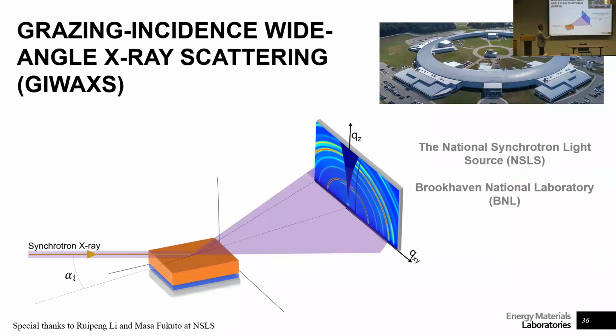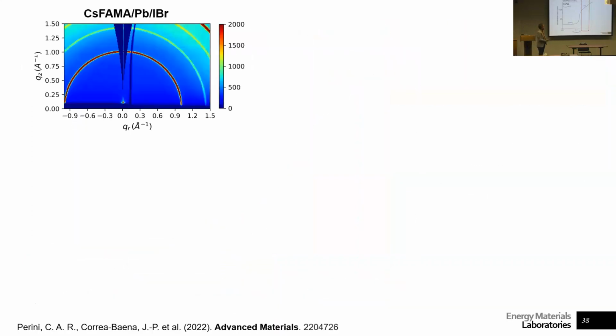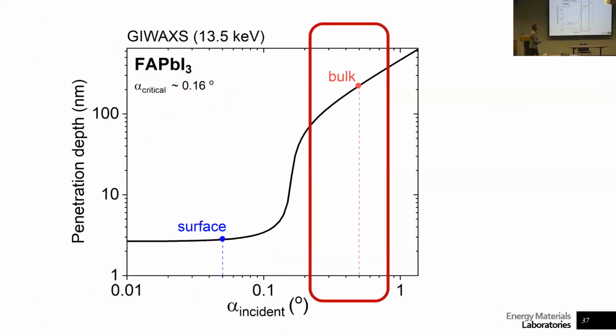And that scattering gives us a signal, and that signal tells us what structures we have in our device. And this is called GIWAXS. And so the lower the angle here, the more surface sensitive we are. And so here is a graph of that. So here is the angle. So really, really low angles, 0.01 degree all the way to 1.